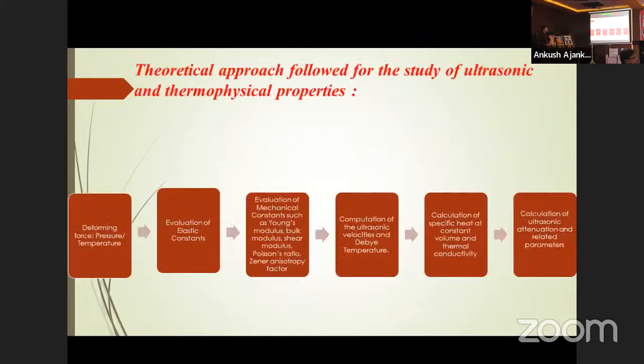In this slide, I have presented the theoretical approach followed by me for the study of ultrasonic and thermophysical properties. First of all, we applied the deforming force in the form of varying temperature. Then, after application of the deforming force, evaluation of higher order elastic constants has been performed, and with the computed values of elastic constants, the mechanical and thermal properties of the specimen have been computed. Further, the specific heat and thermal conductivity were evaluated, and these values were used to compute the ultrasonic attenuation.